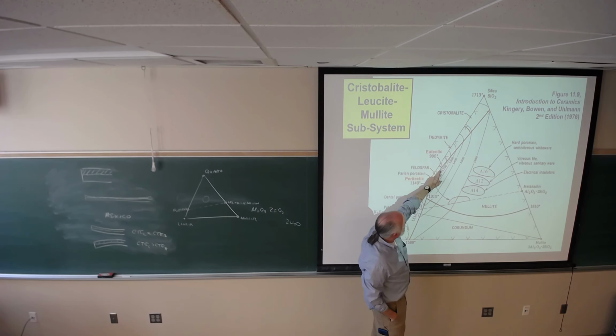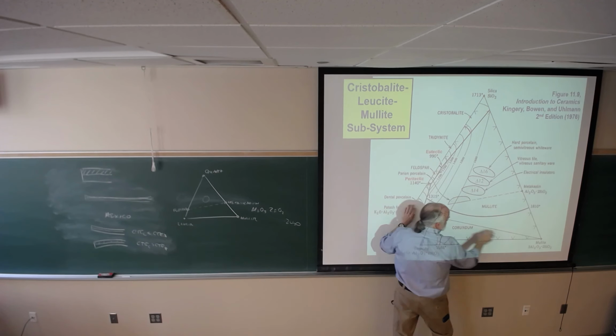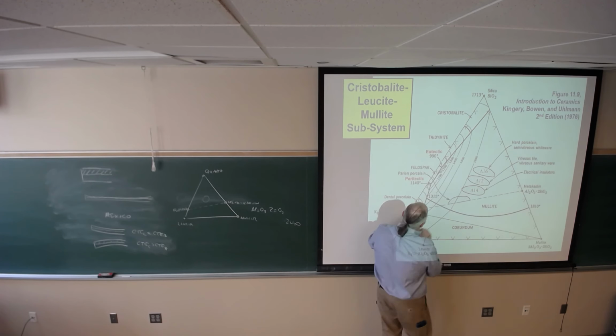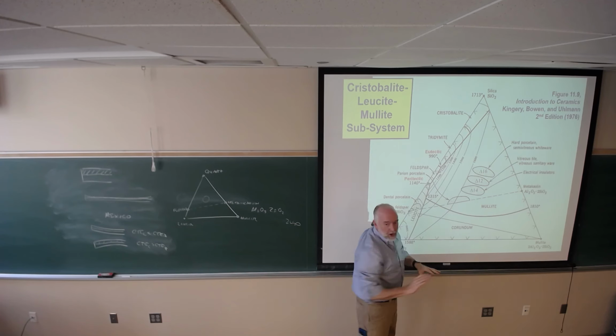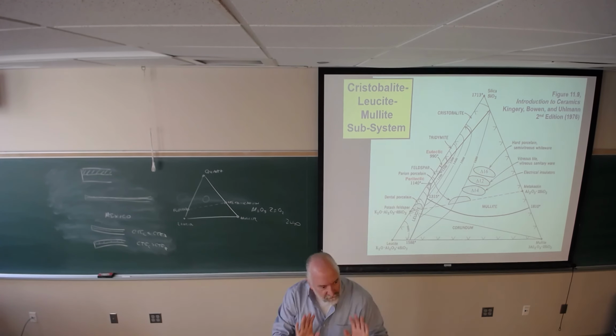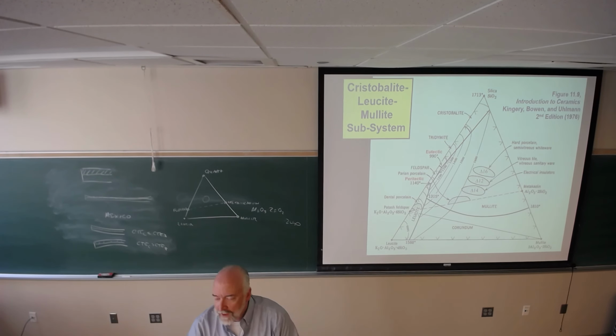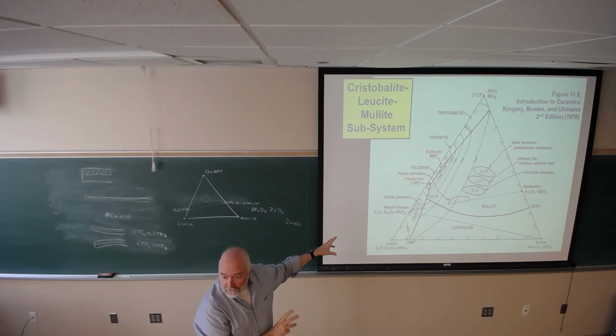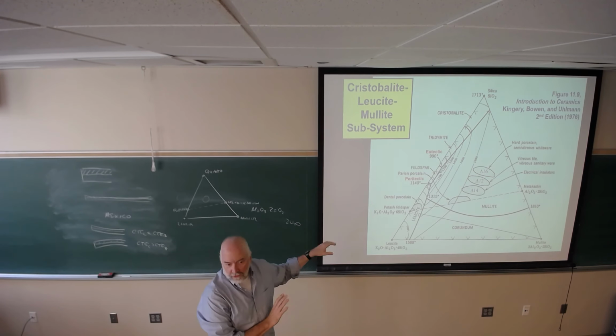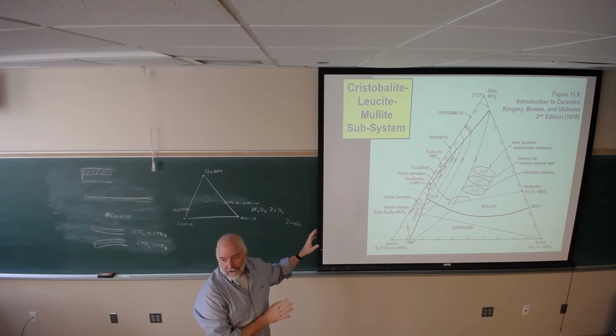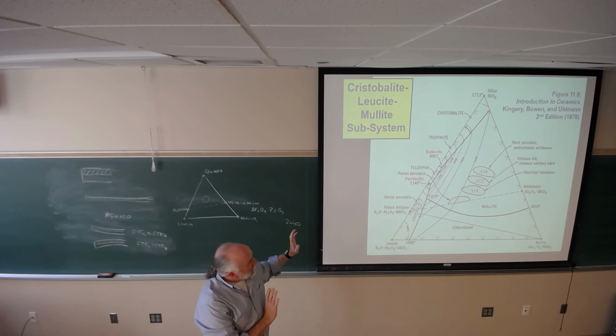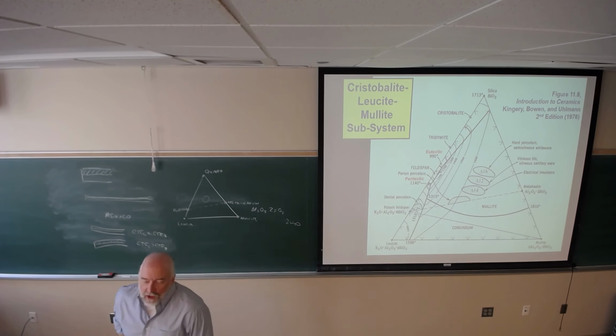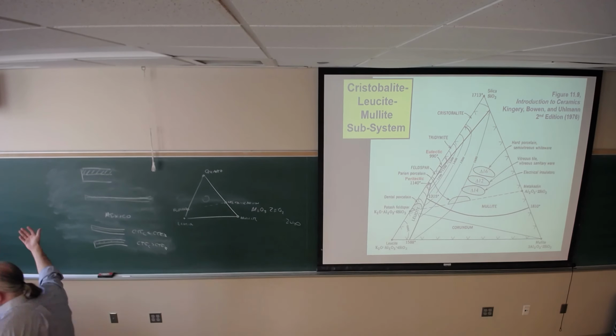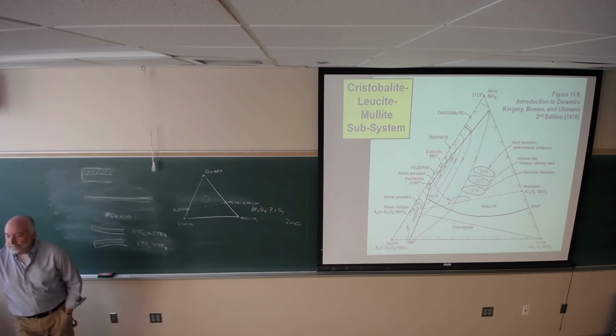So it's a eutectic. That means that anything within this triangle of mullite to feldspar to silica starts to melt at exactly the same point. And that point is the eutectic, 990. That's where the first liquid is formed for any composition which lies within that triangle. Good with that? Okay, you will be. All right. So how come these three bodies have three different firing temperatures? They all start to form liquid at the same temperature.